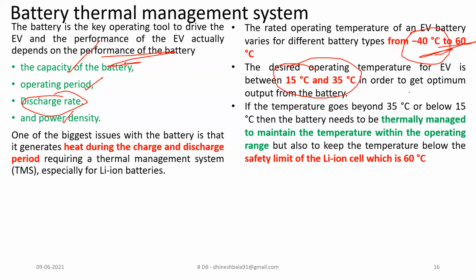So if the temperature goes beyond 35 degrees Celsius or below 15 degrees Celsius, then the battery needs to be thermally managed. We are now very clear about the desired operating temperature range of the lithium-ion battery used in an EV. That lies between 15 and 35 degrees Celsius. So you need to incorporate a system into this battery that should maintain the temperature within this particular range.